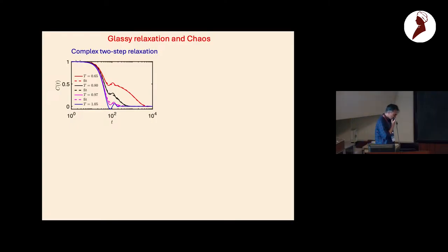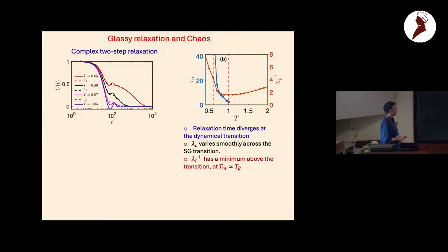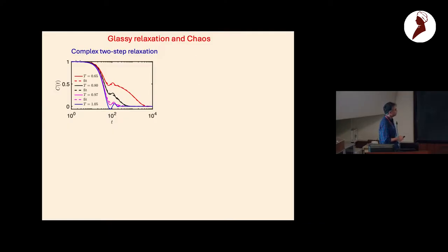Okay, now let me try to connect it to the glasses. Is there any relation with the complex relaxation? What I have plotted here is for the classical limit, so basically h bar going to zero. As a function of temperature, I have plotted the standard plots in glasses, which is the correlation function, like a spin-spin correlation function in this case, at different temperatures. As you go to lower and lower temperature, you start seeing this complex relaxation, basically the beta and alpha plateau, that appears below a certain temperature.